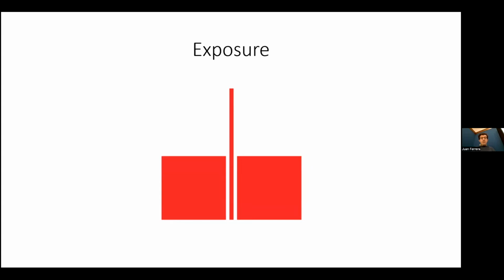And then you go to expose this pattern, which I have here as a cartoon. So let's say that these 2 squares are maybe a micron, and then this line is 1/10 of a micron. So you would imagine if an e-beam writer is the same as a printer, you program it to write this, and that's what you're going to get. But once you do the exposure and you do the development, then what you get is this. So you can see that it's not nearly what you wanted.